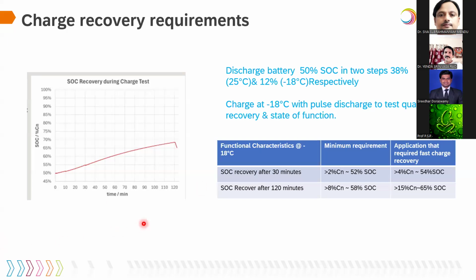We see that within 120 minutes, that means within 2 hours, the battery should reach more than 65% of SOC. That means 65% charging should happen. This is quite challenging even for lithium-ion related storage systems, at minus 18 degrees centigrade, the temperature where these batteries need to be responsive. If it is not responsive at that temperature, then mostly the battery will not be selected as an ideal solution for electric or plug-in hybrid.